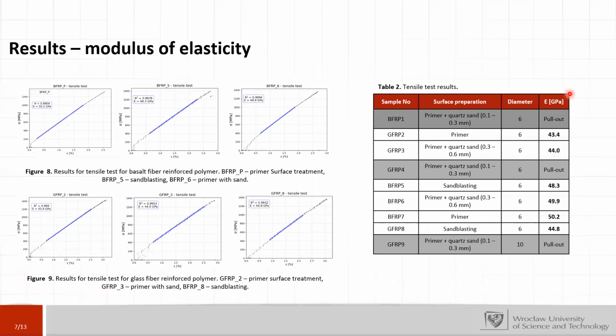As you can see in the table, we put here the value of the Young modulus, and also, from the 9 samples, 3 of them did not withstand the applied load. It means that the adhesive strength was not enough and we had a pull out. So we could not determine the Young modulus, and mainly the primer with quartz sand up to 0.3 millimeters was not a sufficient way to prepare the surface for adhesive strength increasing.